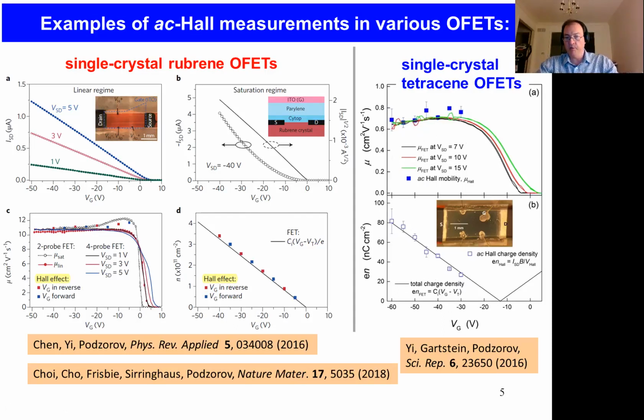So initially, at the time of this measurement, it was a mystery. How can that be in the system with such a low mobility? The reason this is a mystery is because it was believed that organic semiconductors with mobility lower than 1 cannot be in a band-like mode. They should exhibit a hopping type of transport. And if that was the case, then how could we see a Hall effect in the system, and especially fully band-like Hall effect, fully developed Hall effect?